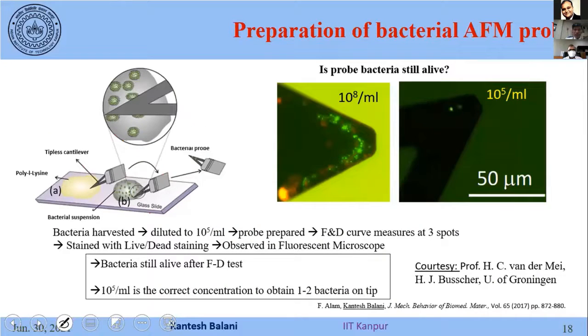So I take this tipless cantilever, I bring it into a solution, and then I have a glue. The glue is strong enough, and I would only want 1 or 2 bacteria, not more than that. I just want 1 bacteria, and then I take it and bring it in contact with the substrate, and then I can basically see the detachment force. To check that I am getting only 1 bacteria, there were 10⁸ bacteria in this solution of 1 ml, but that was leading to attachment of multiple bacteria. Green is a live bacteria, red is a dead bacteria, but I can see there are so many bacteria which I do not want.